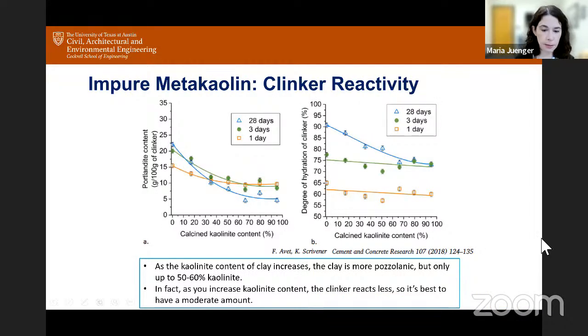There's even, and this comes from work from Francois Avet and Karen Scrivener, but to me this plot is really meaningful, so I'm sharing it with you because I think this is an incredibly valuable plot. What this plot shows you is Portlandite content versus calcined kaolinite content. So if we're looking at something, for example, that has a 25% kaolinite content versus, let's say, a 90% kaolinite content, that's what this x-axis is, and the colors are at different ages.